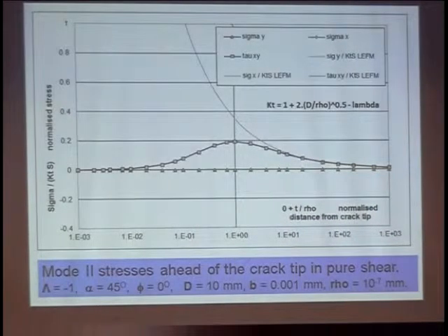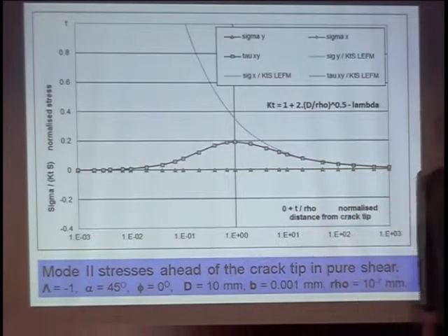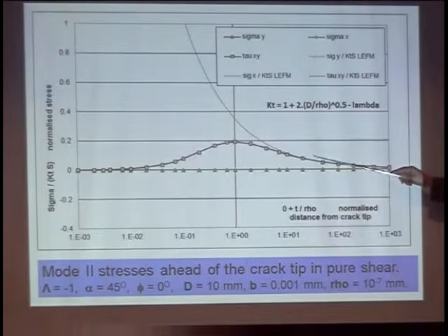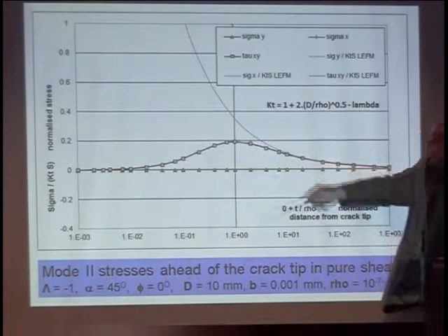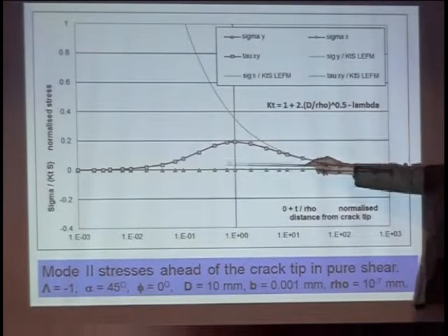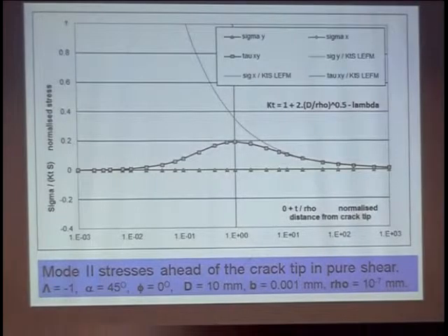This is mode 2, which is the point of the talk really. Phi equals 0, so it's straight ahead of the crack, and we find there's a shear stress here. Sigma x and sigma y are both 0 on the horizontal axis. And again, we have our fracture mechanics result, which is giving quite a different answer.